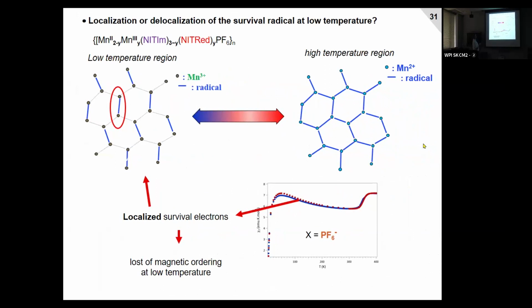And it was easy to finally fit, if we have here at room temperature, this system. So one, these radicals are here. Now we have manganese 3, and one localized radical. So we have a system of 2 spin and 1 radical, and we can fit the system. So in the case of PF6, we can say that the still alive radicals are localized.